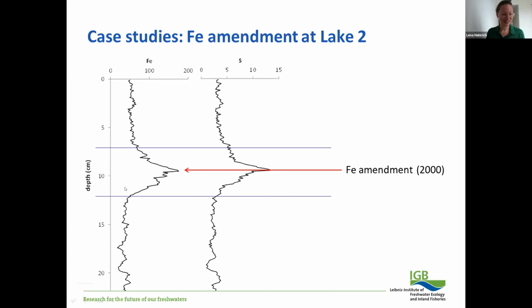But instead of the phosphorus in this sediment, sulfur clearly coincided with iron in the profile. The units of the iron and the sulfur are not contents, but they are counts from micro-XRF scanning. And we also identified pyrite over this whole profile, but approximately twice as much within this iron peak.